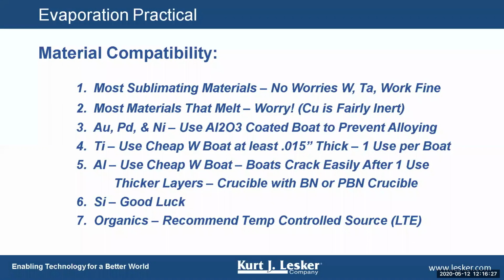Gold, palladium, nickel, they use generally alumina coated boats or alumina crucibles in order to heat them up. And we're talking resistive evaporation here, not E-beam. But the Al2O3 coated boats prevent the gold, palladium, or nickel from wetting to the boat, and you can pull the material out of the boat in many instances after the evaporation is done, because the material does not wet to the Al2O3 coating.